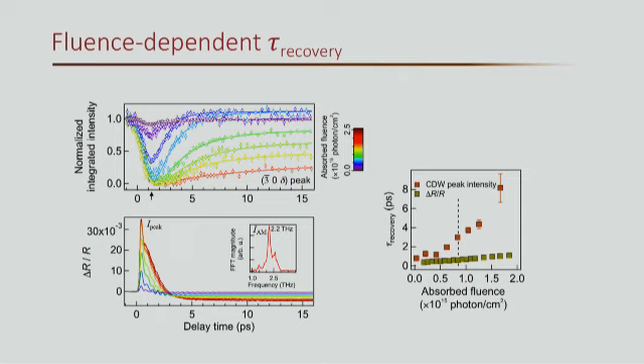Is that permanent, or does that eventually recover? That's pretty much permanent within our probe time window, and that's basically due to heating effect. As we pump a lot of power into the sample, it gets heated up, and that's just a reflection of the thermal change of the reflectivity. It's not damaged? It's not damaged, yeah. It's not damaged because this is not just one pulse. It's repeated pulses, meaning the curve is reproduced every single time a pulse arrives.